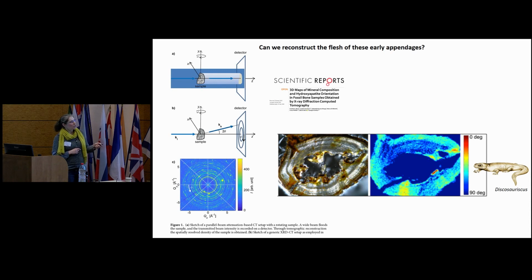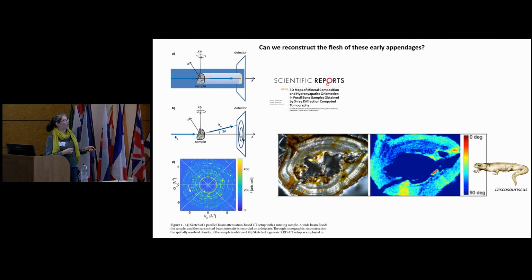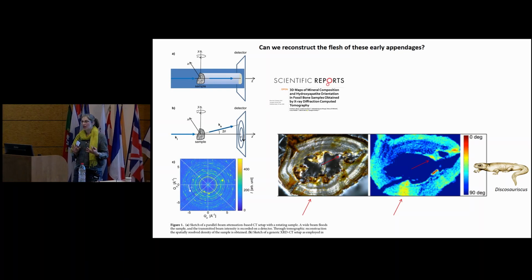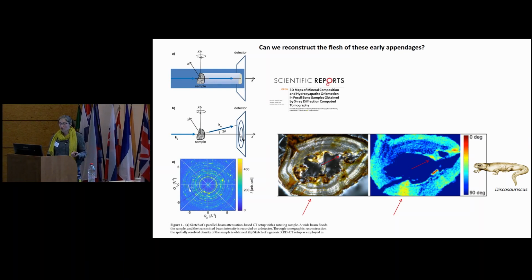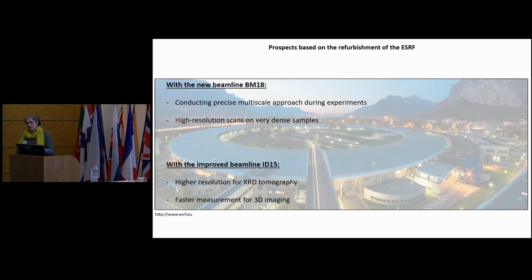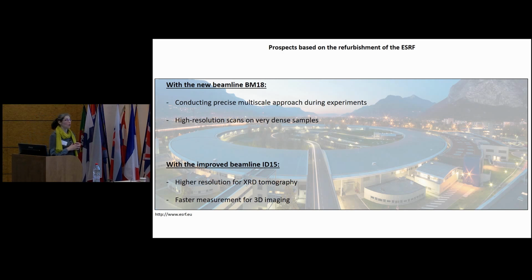So this is a cross-section of the tibia, I think. And you can see that you have a disturbance of the orientation in that direction and in that direction, as you can also see with polarized light, because we checked that with polarized light, here with this thin section, here and here. So for the first time with this technique, we were able to image and map the muscle insertions. So now the big challenge will be to do it at high resolution, as we were able to do on a 2D thin section, but in 3D.